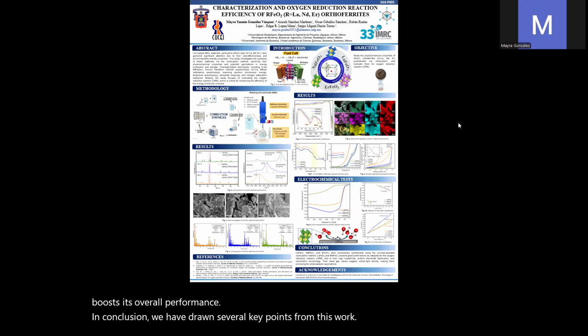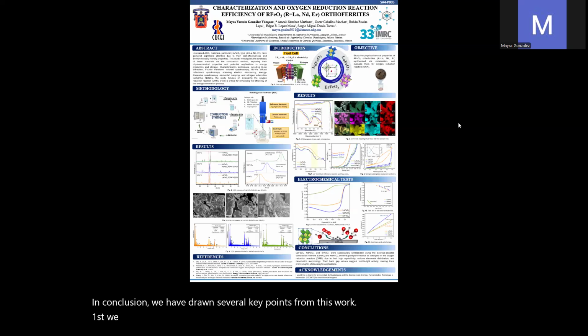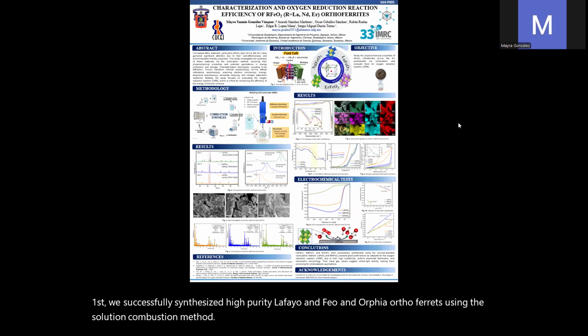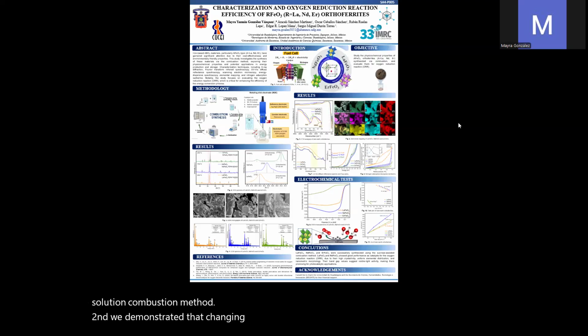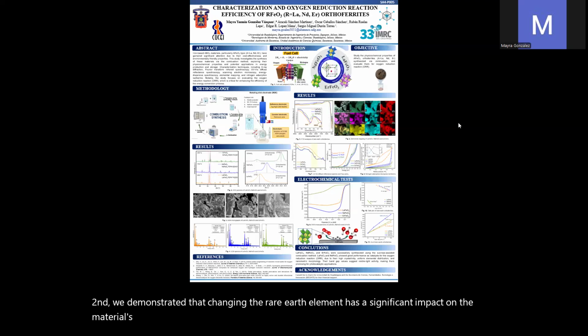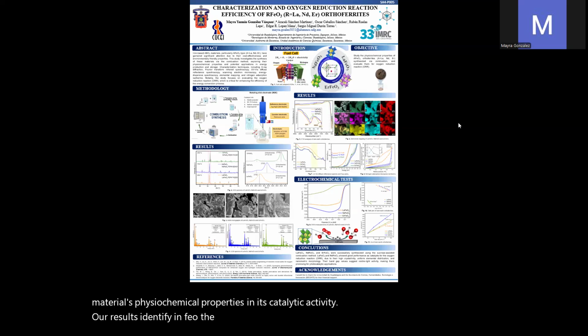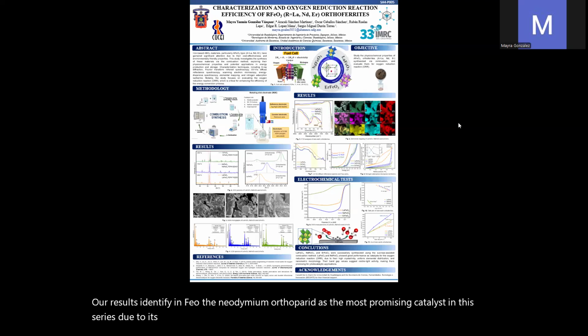First, we successfully synthesized high-purity LaFeO3, NdFeO3, and ErFeO3 orthoferrites using the solution combustion method. Second, we demonstrated that changing the rare earth element has a significant impact on the material's physicochemical properties and its catalytic activity. Our results identify NdFeO3, the neodymium orthoferrite, as the most promising catalyst in this series, due to its excellent properties and higher active surface area.